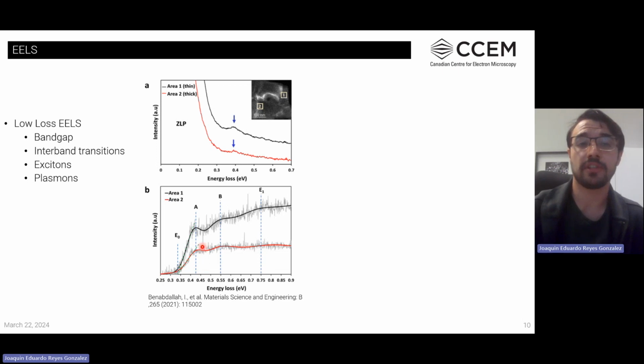And then we can also observe some other type of excitation. So here we have two excitonic peaks and an interband transition forming. And in this particular case, you can see how sensitive it is to changes in the intensity as a function of the material thickness.